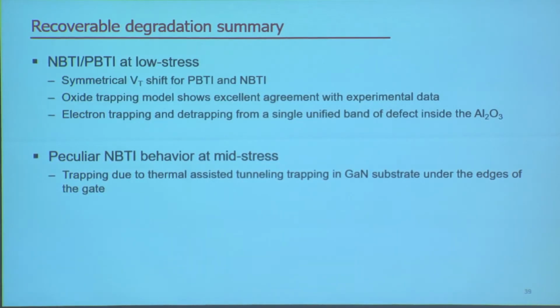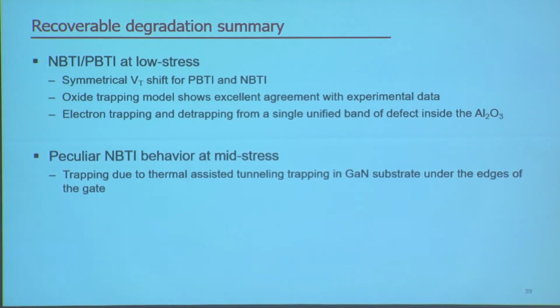So to summarize what we have talked about so far regarding the recoverable degradation of the BTI, first, at the low stress regime, we see a very symmetrical behavior of VT shift for PBTI and NBTI. And we believe that this is due to oxide trapping and detrapping in one single defect band within the aluminum oxide. And our data match very well with the oxide trapping model that people have studied in other material systems, as well as gallium nitride MISHEMTs.